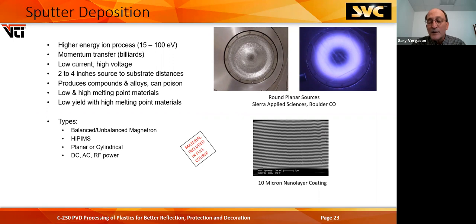But if you're doing reactive depositions, the surface of the cathode can poison, or you know, if you're doing nitrides, it can nitride over and lose conduction. It's great with high and low melting point materials, but the yields are a little bit lower on high melting point.